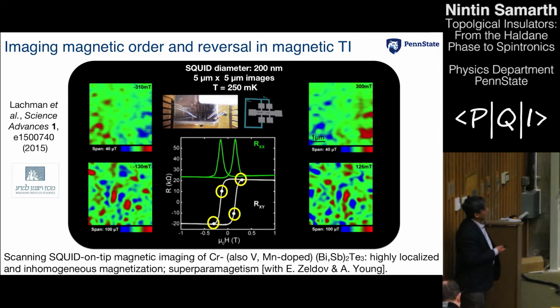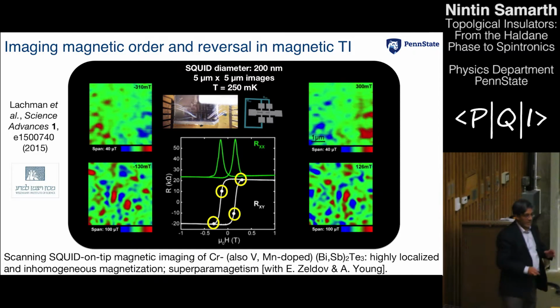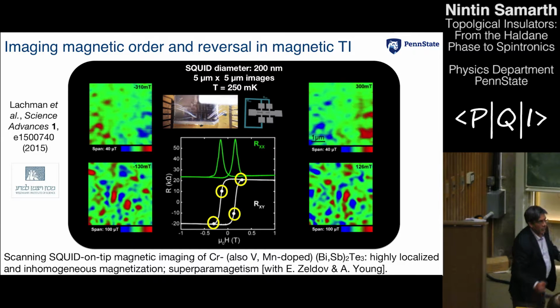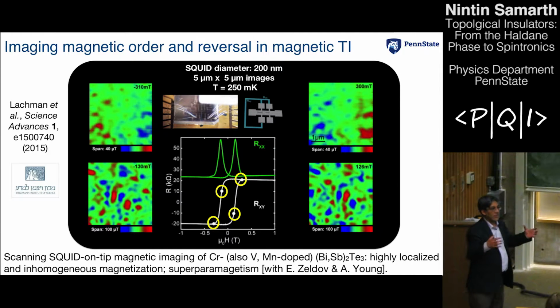And if you now go ahead and saturate the magnetization, surprisingly, it looks sort of like this, where there are some domains still that exist, even though you've swept all the way here. And when you go back to this state over here, which is on the other side of the magnetic field axis, just the negative of this positive over here, you find that you get an image that again looks like this. And if you look very carefully, you'll see that for every blue region over here, there's a red region over here. So in other words, the way this magnetization is switching is not by the growth of domains and the propagation of domain walls, but rather by a very localized kind of switching of the magnetic domains.